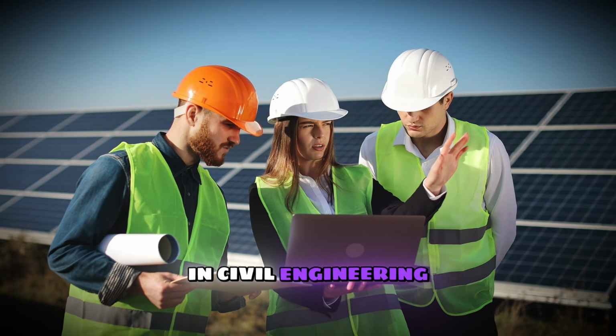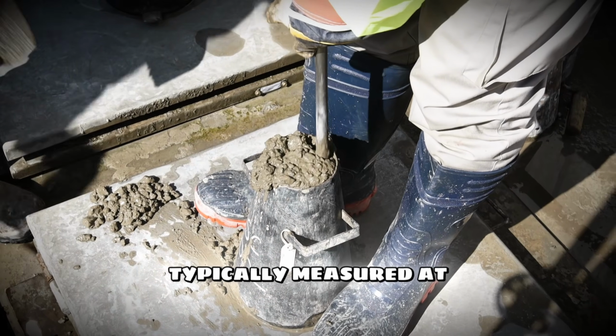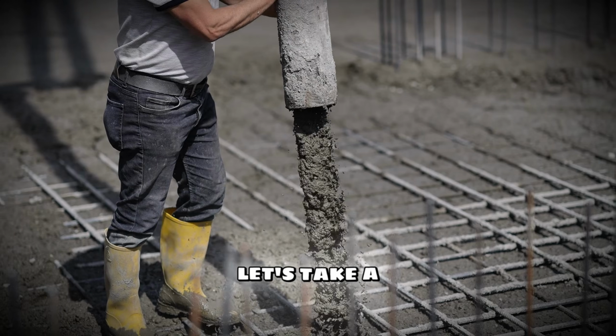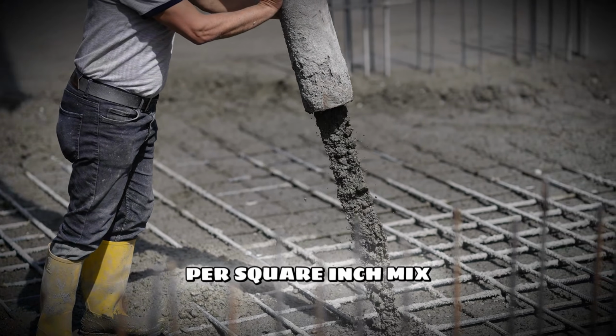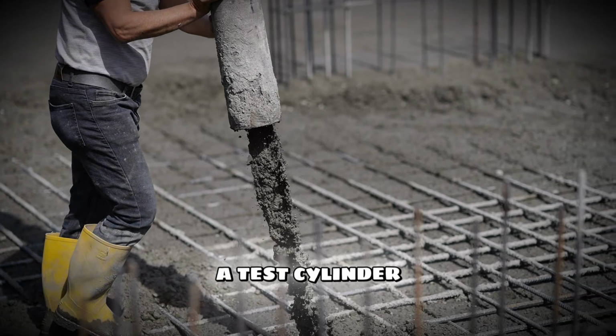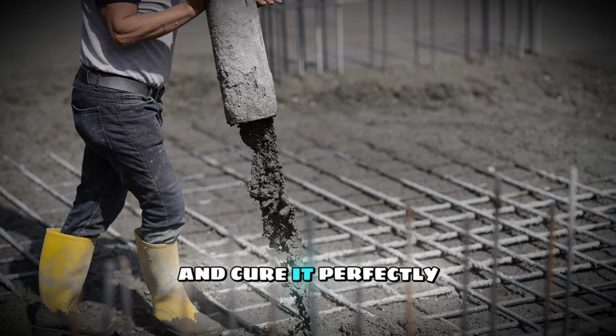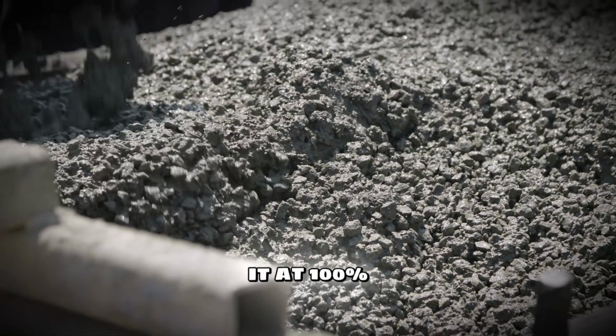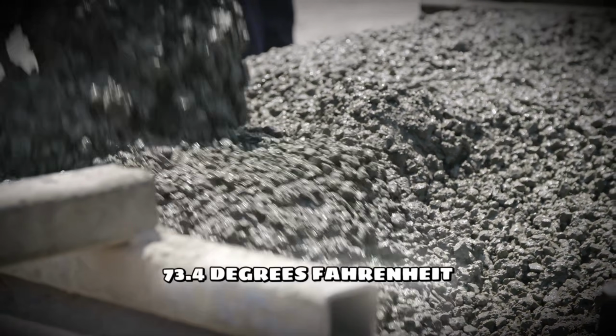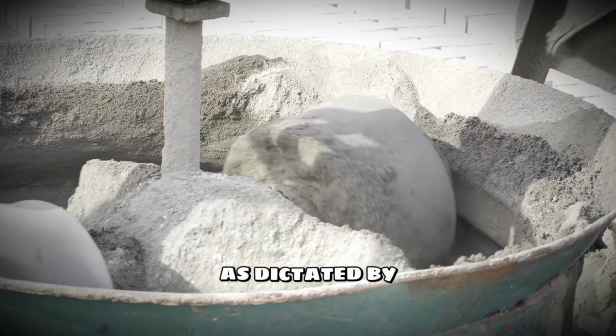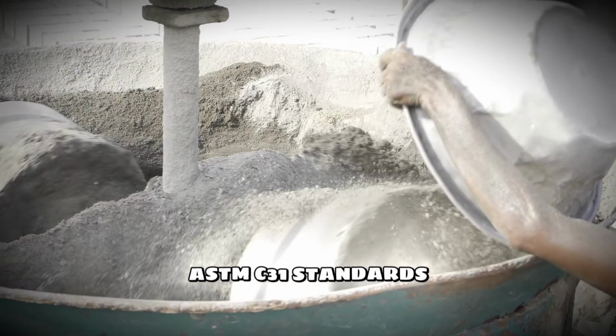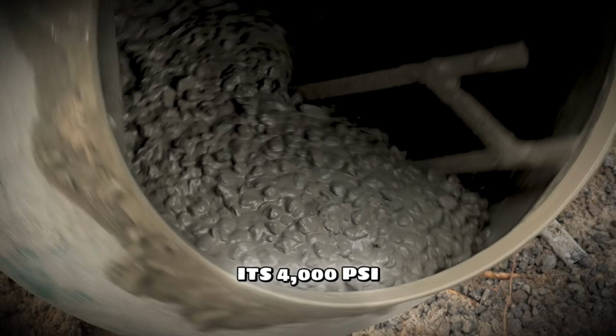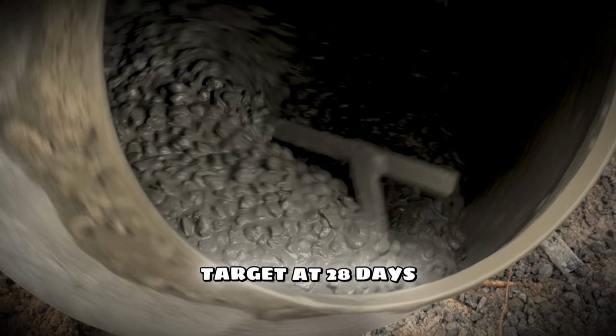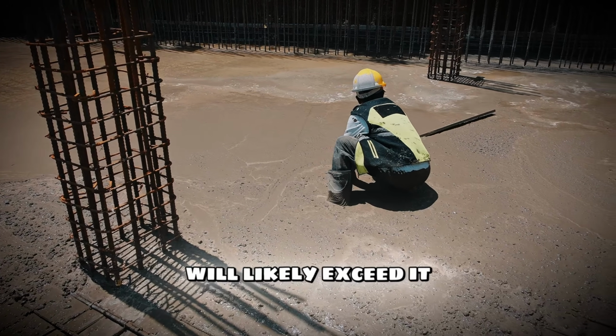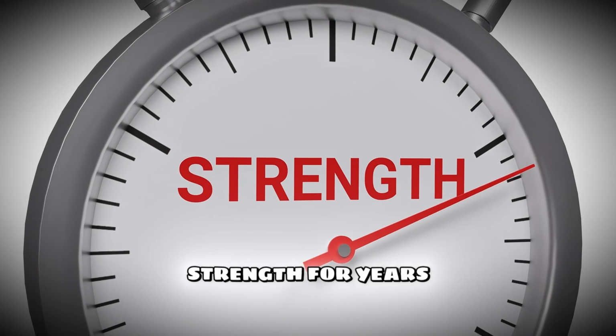In civil engineering, concrete strength is typically measured at 28 days. Let's take a standard 4,000 pounds per square inch mix. If you take a test cylinder of that concrete and cure it perfectly, meaning you keep it at 100% relative humidity and a stable 73.4 degrees Fahrenheit, 23 degrees Celsius, as dictated by ASTM C31 standards, it will hit its 4,000 PSI target at 28 days. In fact, it will likely exceed it, and it will continue to gain strength for years.